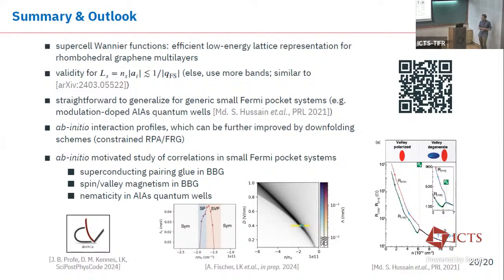We also managed to write down ab initio interaction profiles in this basis, and on a side note, we could further improve those by doing constrained RPA or even constrained FRG to write down the actual screened interaction in the effective model. And in general, we now have a framework to do ab initio motivated study of correlations in small Fermi pocket systems, which would include the question about the superconducting pairing glue in Bernal bilayer graphene, of course, spin and valley magnetism in Bernal bilayer graphene, and as I said before, nematicity in those aluminum arsenide quantum wells.